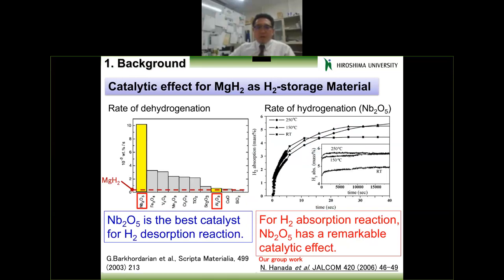So it was a slightly long time ago, one German group focused on magnesium hydride. And magnesium hydride is quite a typical material for hydrogen storage because it has quite high capacity. But unfortunately, magnesium itself is quite difficult to treat because of quite bad kinetic properties. Of course, potentially magnesium can absorb hydrogen at room temperature, but usually quite a high temperature is necessary for kinetic reasons. And usually before our report, many researchers focused on magnesium hydrogen absorption properties at more than 300 degrees C because of the bad kinetic properties.